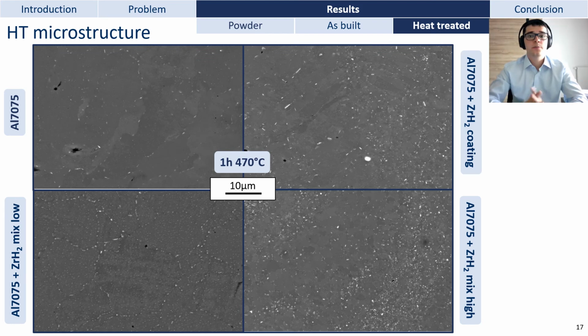Now that the as-built microstructure has been analyzed, let's see how heat treatment will affect the microstructure. The classical T6 heat treatment used for the aluminum 7075 will be analyzed. It is thanks to this heat treatment that the 7075 obtains its higher strength by controlling its precipitation.